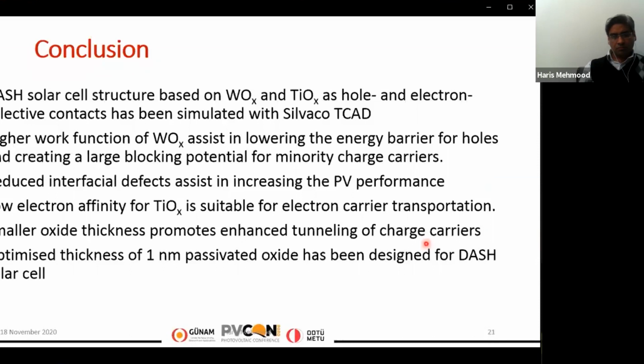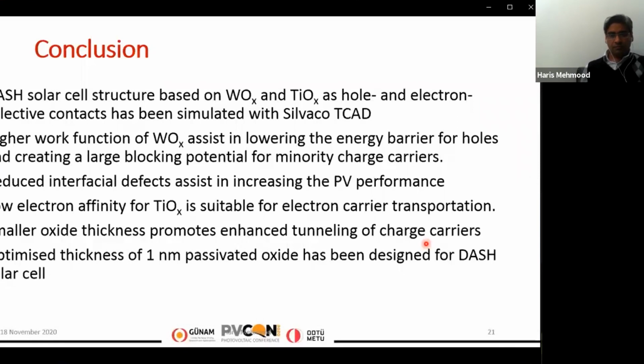So, conclusion: the solar cell structure based on tungsten oxide and titanium dioxide as hole and electron selective contacts has been simulated with Silvaco TCAD, and the higher work function of tungsten oxide assists in lowering the energy barrier for holes, thereby improving the photovoltaic performance, and the reduced interfacial defects assist in increasing the photovoltaic performance, and a low electron affinity has to be used for the titanium dioxide.